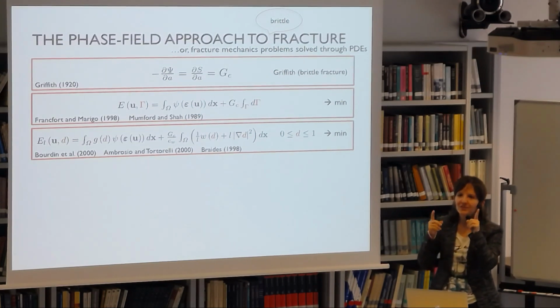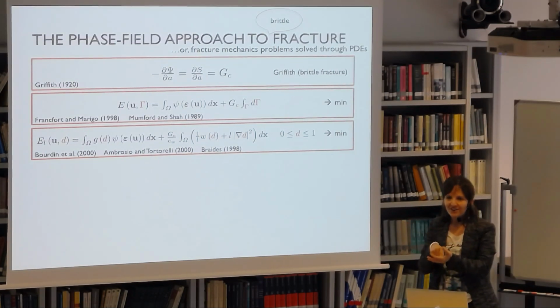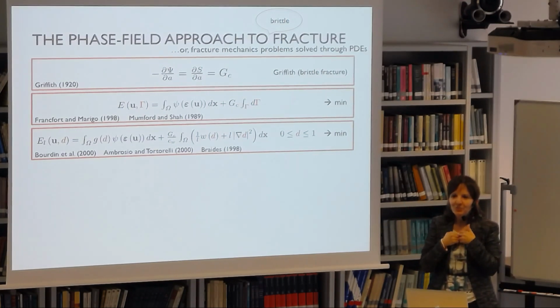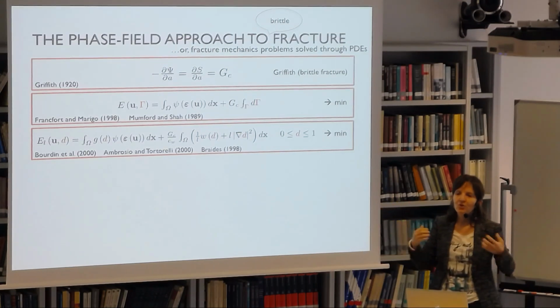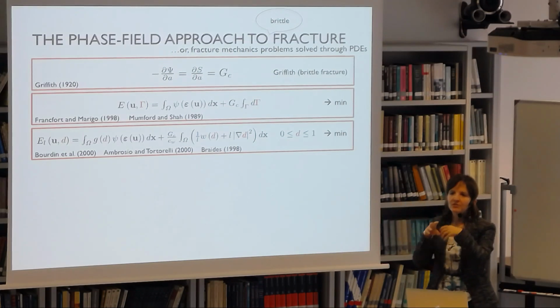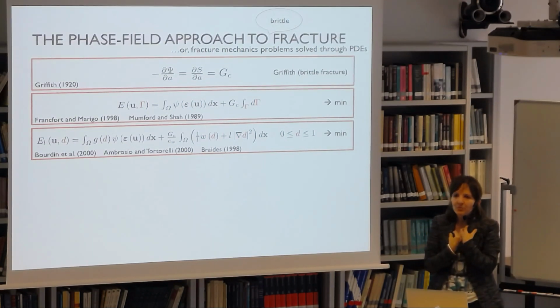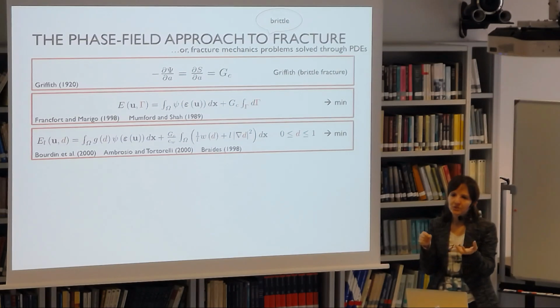Either this L is much smaller than the specimen size, then everything is fine. But if L is too large for the specimen size, my personal opinion, which we debated in Banff a month ago, is that this is a clear indication that your material is not brittle enough to be studied with this method. In the end, brittleness is also a matter of the ratio between the process zone and the size of the specimen. So if you compute L for a given material based on the critical stress, and you find that L is too large for your specimen size, this indicates that the specimen is too small to study fracture as a brittle phenomenon, because your process zone size is comparable to the structural dimensions.